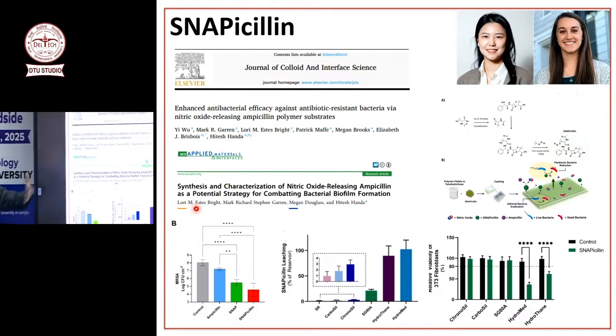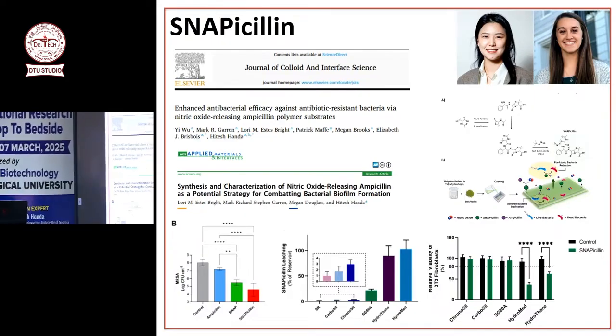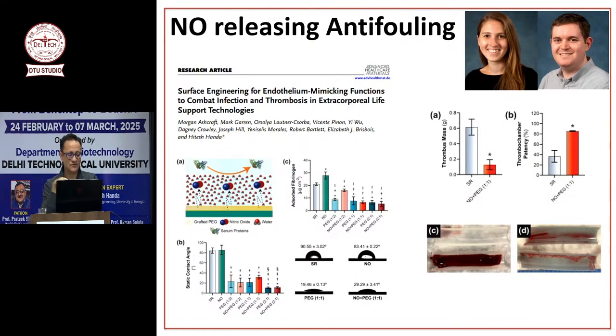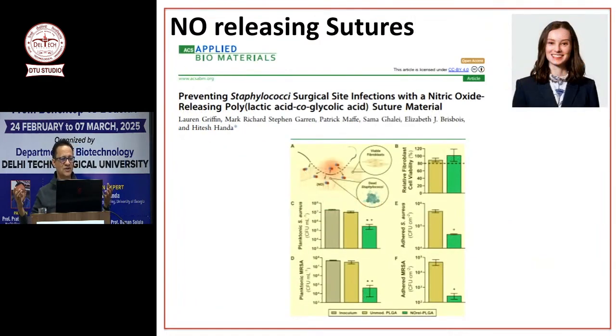So one paper is more solution, snapicillin. One paper is more polymer, that has snapicillin releasing properties. NO releasing anti-fouling surface, we did an animal model on it also, the ECC 4-hour model. And you can see the contact angle. When you had only the NO surface, the contact angle was high. When you had the NO releasing anti-fouling surface, contact angle was much lower, and it worked great in the animal model also. The last one is NO releasing sutures. So we made PLGA NO releasing sutures, which can now fight infection and reduce infection, and over time the suture will go away anyways. So that's the idea with NO releasing.